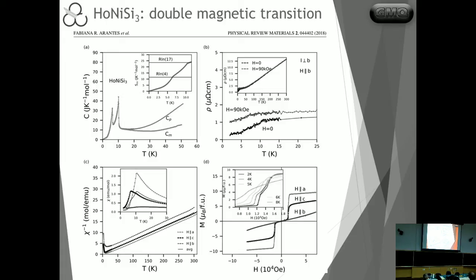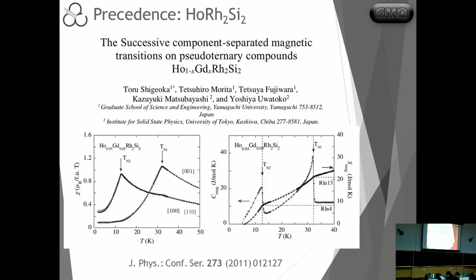But Fabiana did a search on this, and she ended up finding one precedent for this type of situation, which was found in the case of the holmium rhodium 2 silicon 2 system, again showing two different Néel temperatures for two different directions. And the proposal here is that what is happening is known as component separated magnetic ordering. So it seems that at the higher temperature there's one component of the magnetic moment that orders, but the other one just remains unordered. And then finally at the lower temperature you do get a full ordering there. But of course this is just a proposal.